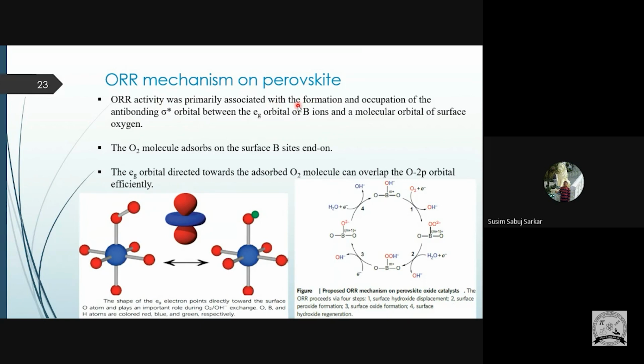ORR activity was primarily associated with the occupation of the antibonding sigma star orbital between the Eg orbital of the B ion and the molecular orbital of the surface oxygen. That means the oxygen which is coming will be forming a bond with our B metal, the transition metal B site of this perovskite. You know that for the transition metal d orbitals in an octahedral field, they split into T2g and Eg, and the Eg will be the higher state. So the Eg orbital of the B ion and the antibonding orbital of the molecular oxygen will form a bond.